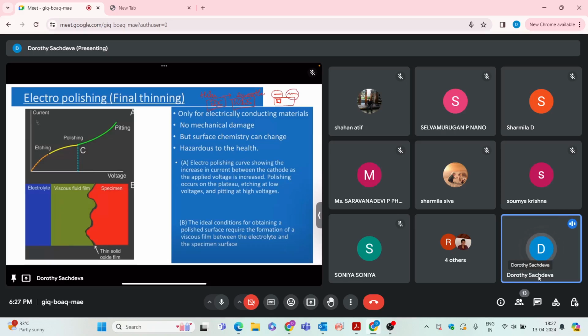So when you want to do WDS, if you have an electropolished sample, then it will give very good results as compared to a rough sample. This is used only for electrically conducting materials. There is no mechanical damage, but the surface chemistry can change because of the electropolishing. The electropolishing curve shows the increase in current between the electrodes as the applied voltage is increased. Polishing occurs at the plateau in this region, shown by this yellow curve. Etching occurs at low voltages and pitting at high voltages. The ideal conditions for obtaining a polished surface require the formation of a viscous film between the electrolyte and the specimen.